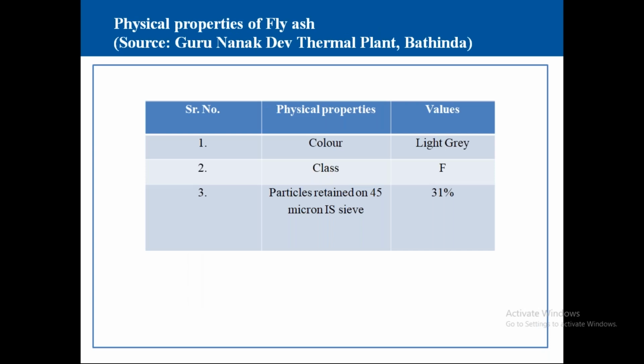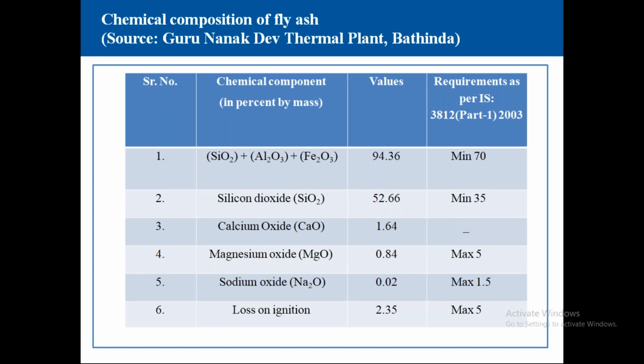As far as the properties are concerned, these are the physical properties of fly ash. It was F type, and the particles retained were 31%. As far as the chemical properties are concerned, the value of SiO2 plus Al2O3 plus Fe2O3 is 94.36%. As per the codal recommendations, the value should be more than 70. Silicon dioxide is 52.66, again the minimum value is 35. Calcium oxide is 1.64. Magnesium oxide is 0.84, and the maximum value specified is 5. Sodium oxide is 0.02. LOI is 2.35.